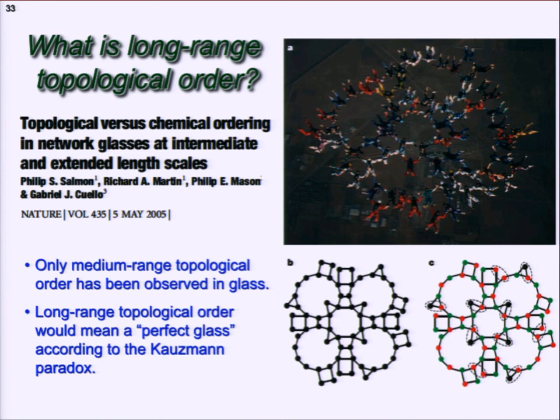Like the difference between glass and crystal. Crystal has a long-range spatial order, so you can do diffraction. You can see it with X-ray diffraction, neutron diffraction, or electron diffraction. You can see the direct peaks. But if you have only long-range topological order, it is like skydivers who all hold each other's hands. If you arrange them very regularly, then of course you get diffraction. But if your hand can stretch and your ankle can bend, you get to a point where you don't see that order anymore. There's no spatial order, but still the connection is there. So that's called topological long-range order.